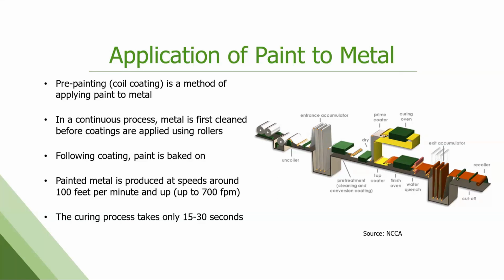The coil starts out, enters the line, goes through a cleaning section, gets nice and prepped for receiving paint. We do use a pre-treatment that goes on to create a good bond with the paint. We put a primer on that gets baked on at high temp. After that, the finish coat gets applied, again at high temp, very quickly. Speeds are anywhere from 100 up to 700 feet per minute, depending on which specific line we're talking about. So it can be very, very fast.